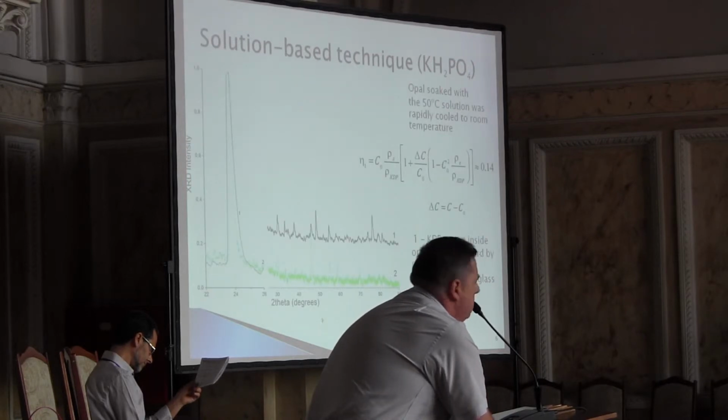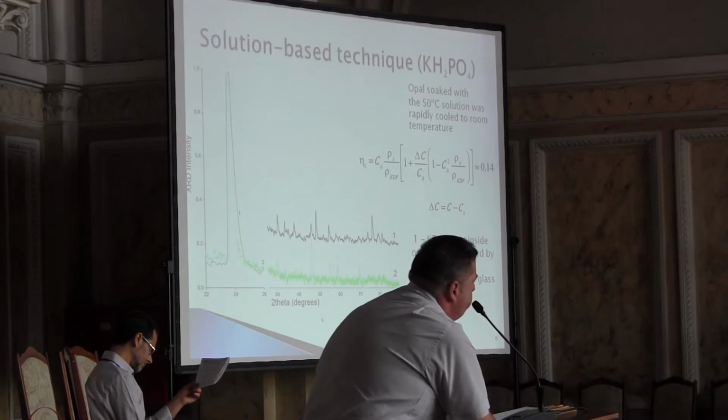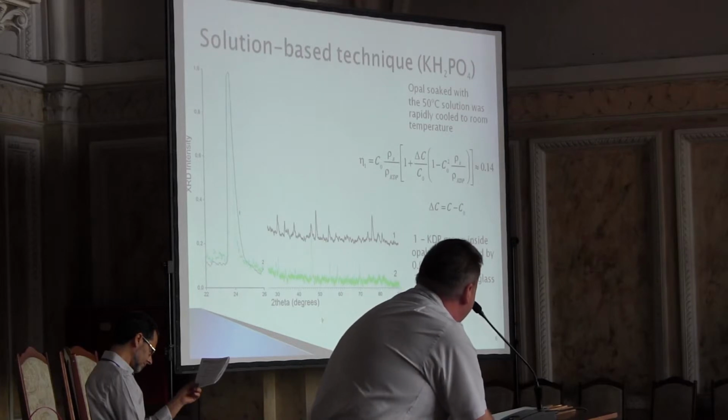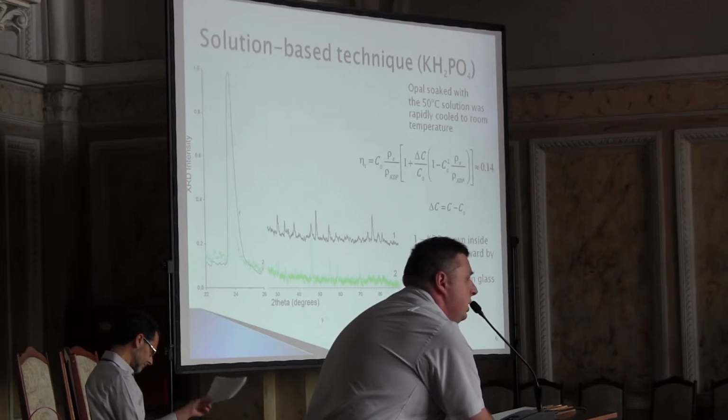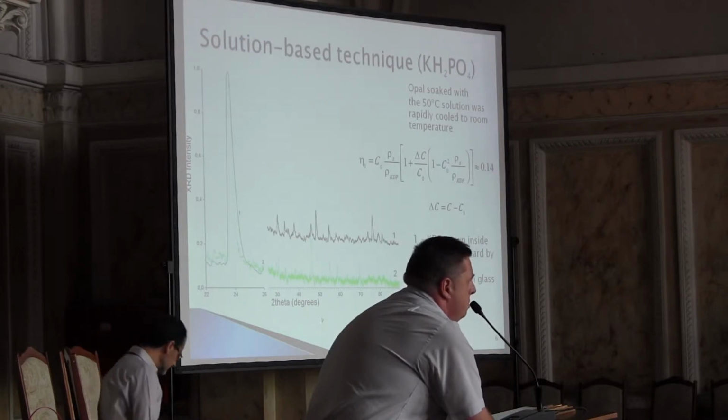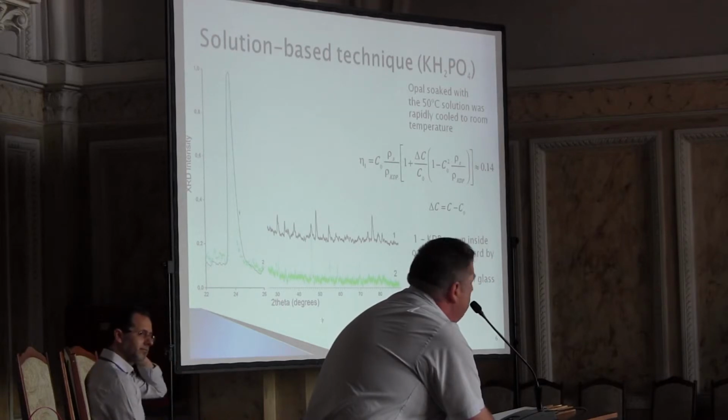The second way of the solution-based technique is so-called non-equilibrium crystallization, when we have a solution at high temperature, at 50 degrees centigrade, and we soak the sample, which is at room temperature, with this solution. We have non-equilibrium crystallization in this case because of rapid cooling of the solution.